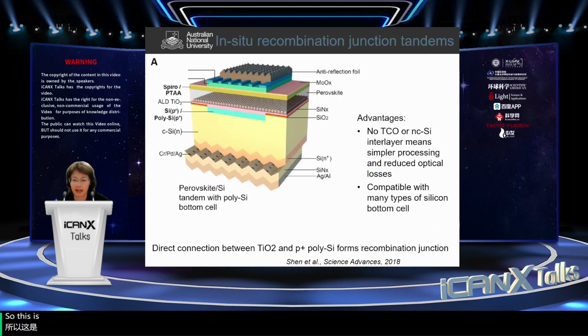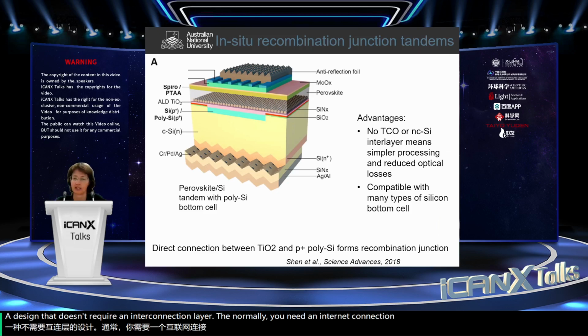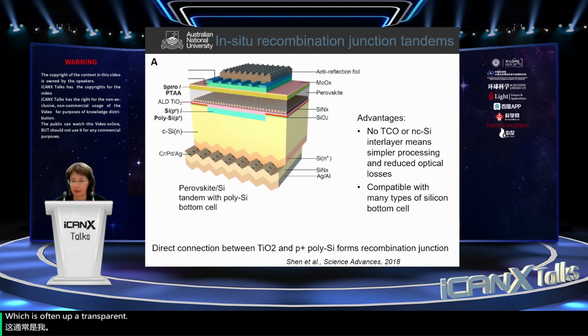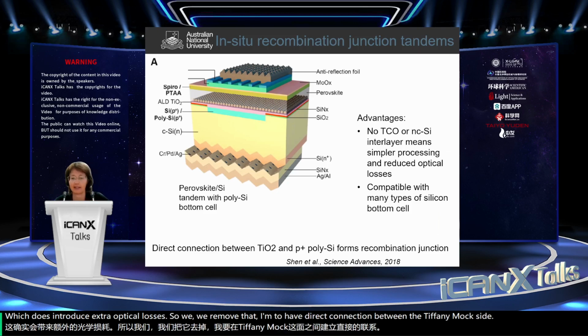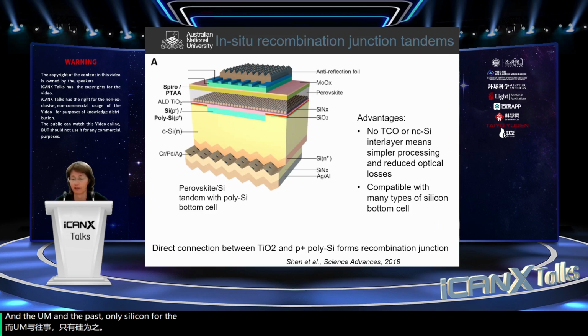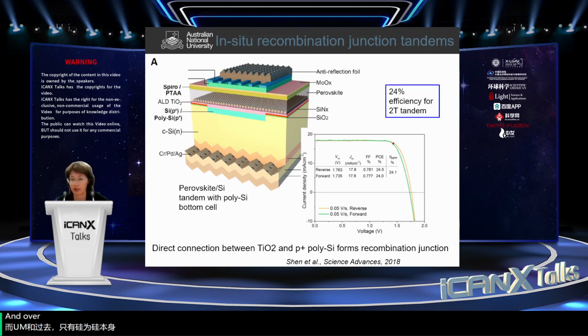So this is some of our first work on 2-terminal tandems a few years ago. We created a new design that doesn't require an interconnection layer. So normally you need an interconnection layer between the silicon cell and the perovskite cell, which is often a transparent conducting oxide layer, for example, which does introduce extra optical losses. So we remove that to have direct connection between the titanium oxide and the P+ polysilicon of the silicon cell. And overall, we're able to achieve 24% efficiency for that 2-terminal tandem.